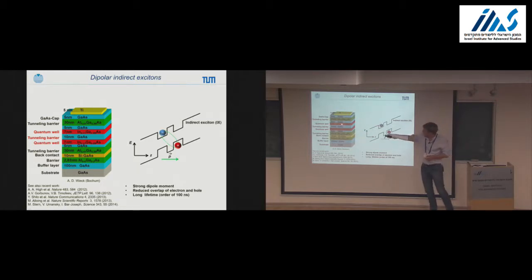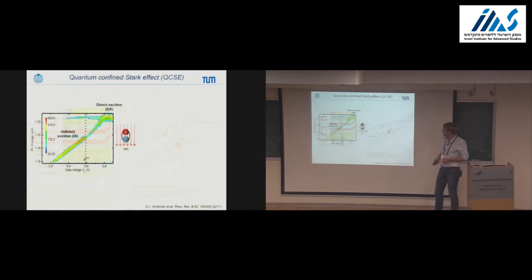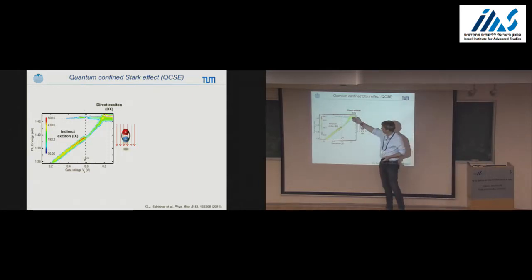When you look at the structure, we have indium gallium arsenide. The backgate is gallium arsenide. That gives rise to a peculiarity. We're not starting with dipolar excitons when we apply rather zero gate voltage. We put titanium on top of the gallium arsenide. There's a Schottky barrier. The height is roughly 0.7 eV, depending a little bit on the surface, on the passivation, the nanofabrication, what you have done to the sample. So we need to apply a positive gate voltage to have flat band.